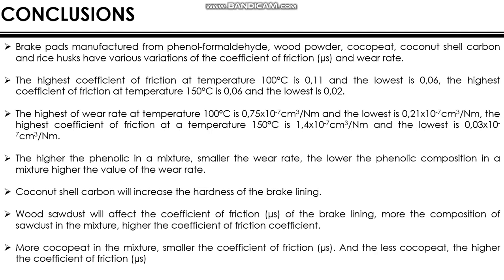The higher the phenolic in a mixture, the smaller the wear rate. The lower the phenolic composition in a mixture, the higher the value of the wear rate. Coconut shell carbon will increase the hardness of the brake lining. Wood sawdust will affect the coefficient of friction on the brake lining. The more sawdust in the mixture, the higher the coefficient of friction. The more cocopeat in the mixture, the smaller the coefficient of friction, and the less cocopeat, the higher the coefficient of friction. Okay, enough from me.